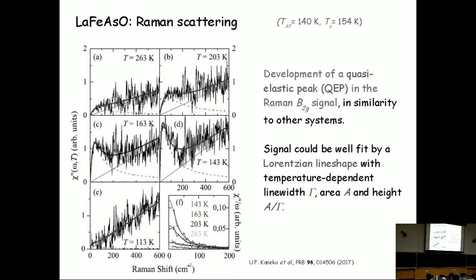And then we cool down again below both the magnetic and the structural transition temperatures, and this signal disappears. So you divide the Raman intensity by the Raman shift, omega, and then you have these curves which are peaked at 0 frequency, and you can fit them very well with Lorentzian curves. That's very characteristic of what you call a quasi-elastic peak, essentially a Lorentzian centered at 0. We are measuring not the peak, but the side of the Lorentzian by Raman scattering. That's a very well accepted feature characteristic of the nematic fluctuation signal by Raman scattering.